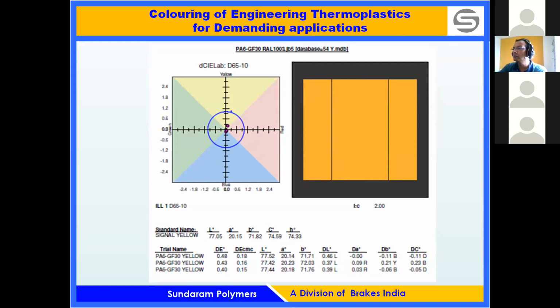Against it, we have a fiber matching this signal yellow color, which is an RoHS compliant material. We have been able to achieve a delta E of less than 0.5 as against the industry standard requirement of less than 1, and delta E CMC is also less than 0.18. So it is a very close match, as you can see visually between the standard and the sample.